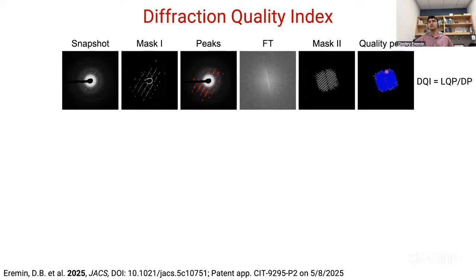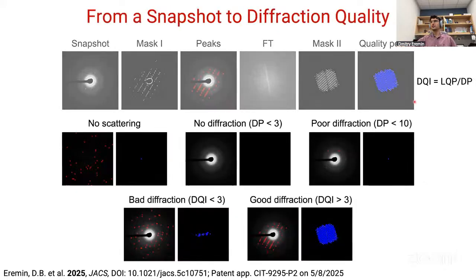These peaks we call lattice quality peaks. If you take a ratio between the lattice quality peaks and the number of the diffraction peaks, you will get the diffraction quality index. Using this index, you can reasonably quickly, with quite good reliability, classify different diffraction patterns. For example, if you have complete garbage, you will have absolutely no diffraction or lattice quality peaks, and you will get basically a no scattering type pattern.